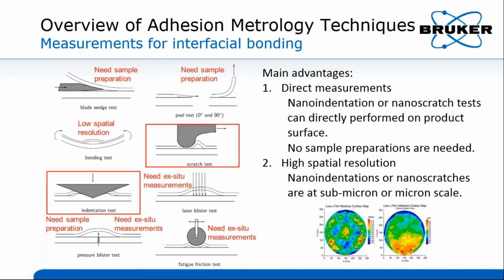Some techniques need specific sample preparations, and some need ex situ measurements. Among all of these techniques, nanoindentation and nanoscratch are really suitable for thin films due to two main advantages. One is direct measurement, where the probe can be directly applied onto the sample surface without any preparations. And the other advantage is high spatial resolution.